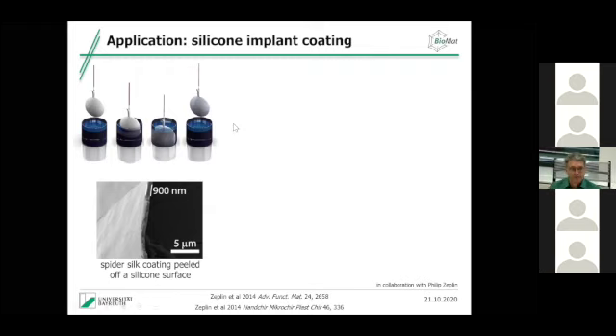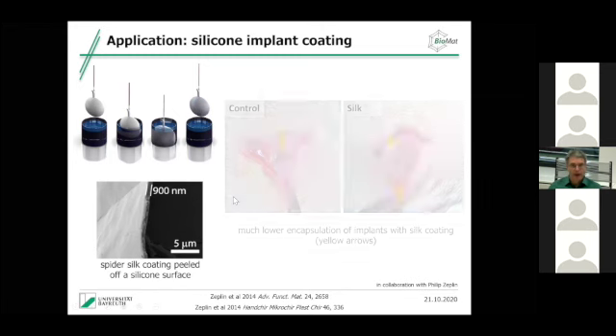How to coat a silicone breast implant? It's quite easy. You just take this implant, you dip it in a silk solution, an aqueous silk solution, I have to say. And silk molecules are amphiphilic. So what happens is they immediately assemble on the surface and they make about a 1 micrometer thick film. So we get then a shielding, a coating of this implant.